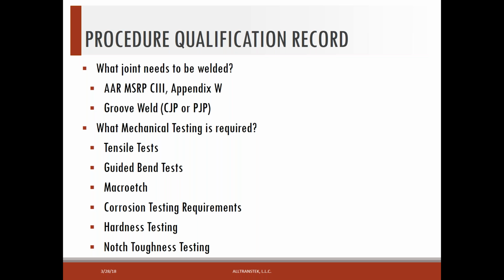You might ask, well, what are examples of partial joint penetration welds? In some cases, the tank nozzle to the nozzle flange in some designs is a partial penetration weld. So we have to do something a little bit different with partial penetration welds as opposed to a complete penetration weld. And what mechanical testing is required? Of course, with groove welds, typically tensile tests and guided bend tests are required to qualify that particular joint.